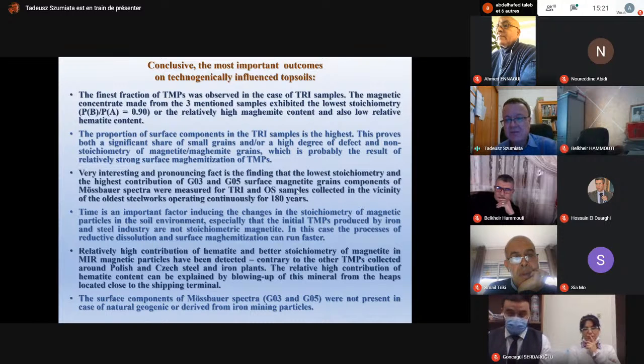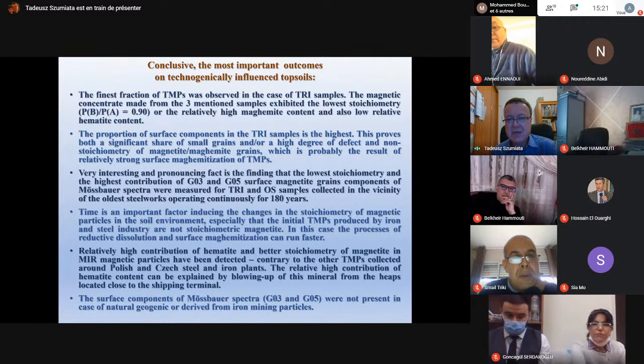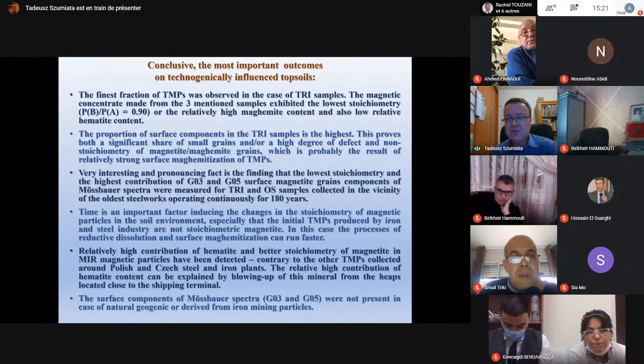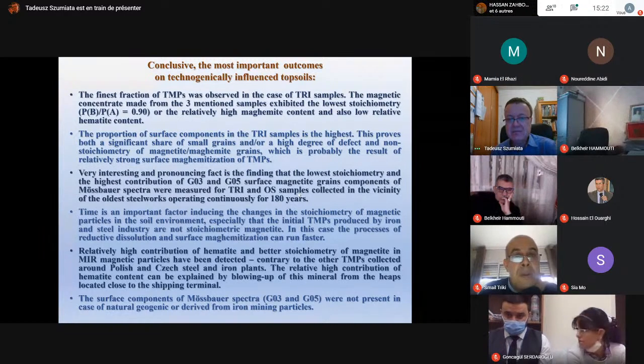Okay, I don't want to read the very detailed conclusion from this part, but I would like to say that we can believe that mineralogy, I mean the contribution of each phase, and also detailed hyperfine parameters of the Mössbauer spectra are good characteristics for these topsoils, for the technogenic magnetic particles inside these soils, and these results from Mössbauer spectrometry could identify the sources of technogenic magnetic particles emission.